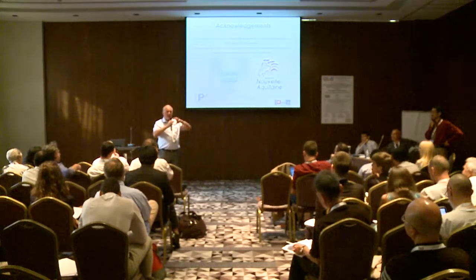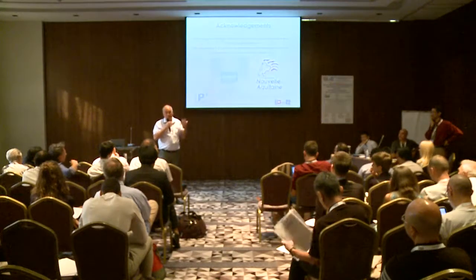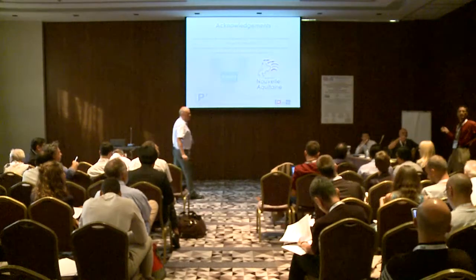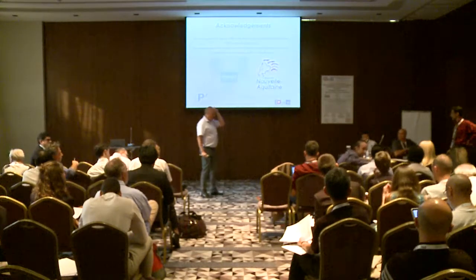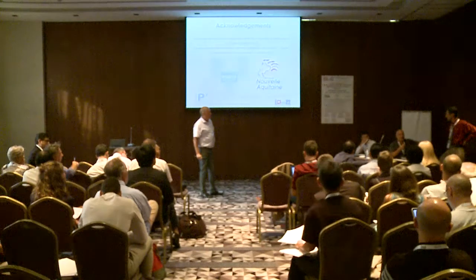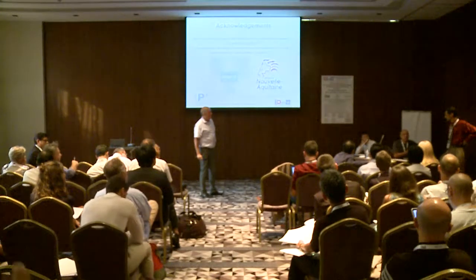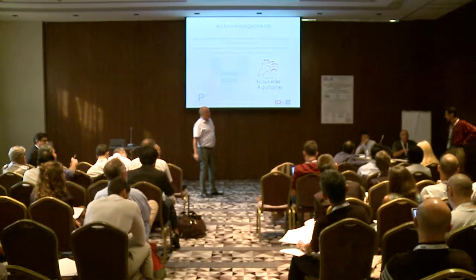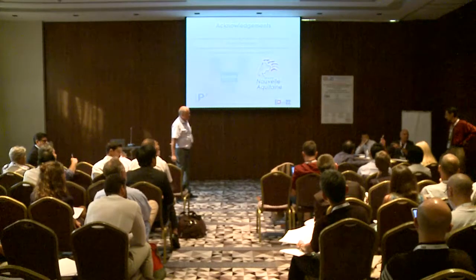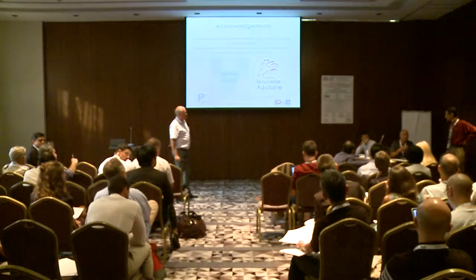I agree with you. The grains are highly deformed when you look, or at least they look highly deformed. If I may add one comment to Professor Rich's question. We did test fatigue test inside SEM and environmental SEM with pressures in the range of 90 Pascal, 80 Pascal, very low pressure. But we see very similar results. So I don't think that the pressure is playing a very crucial role here.